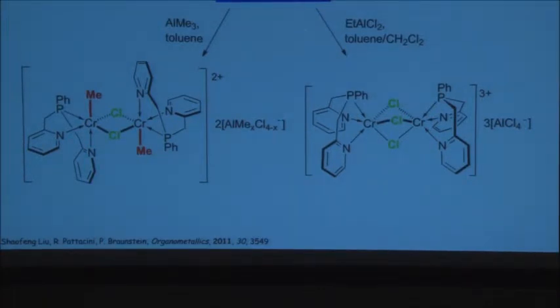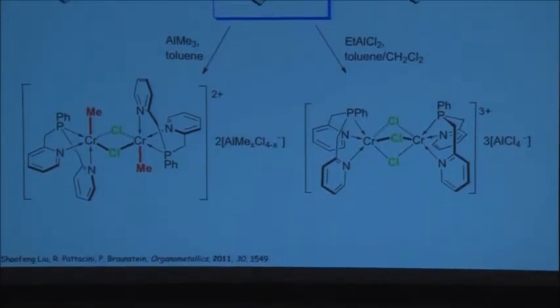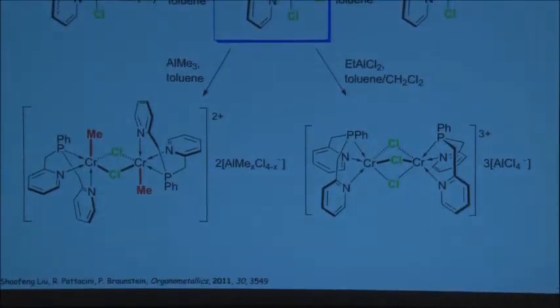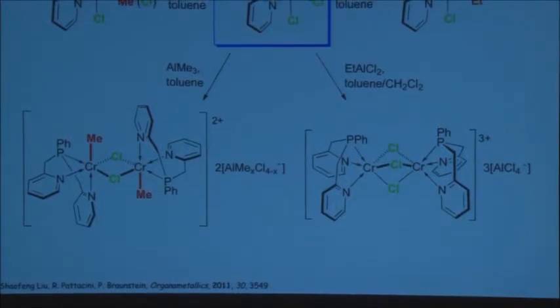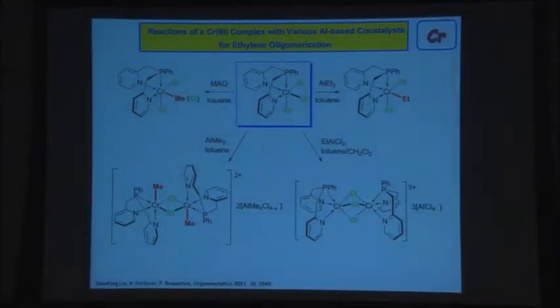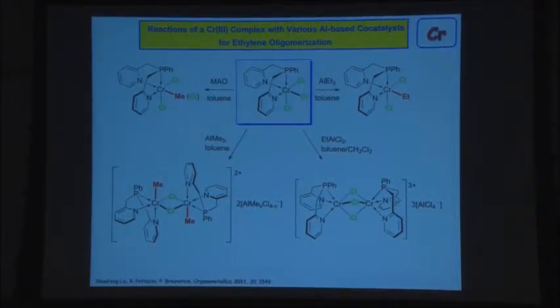And if you take ethylaluminum dichloride, we see no alkylation product, only chloride abstraction to form now this dinuclear species with 3 doubly bridging chlorides. Let me emphasize again, I do not claim that these are the only products of the reactions. These are the products we could characterize. At least it triggers your imagination to think of possible scenarios when you have your precursor reacting with various co-catalysts. Why do some co-catalysts have different function than other co-catalysts? Maybe related to the diversity of products we could isolate in these reactions.